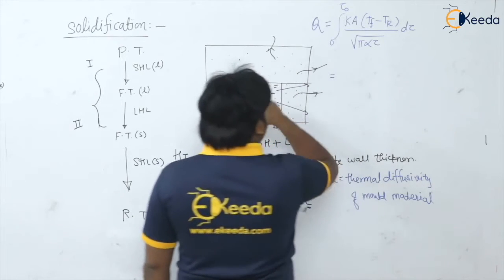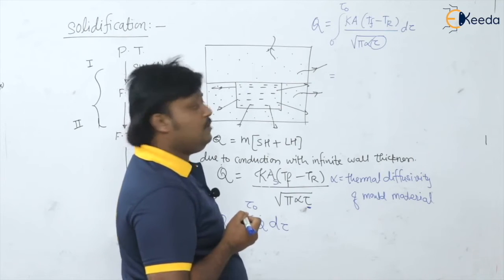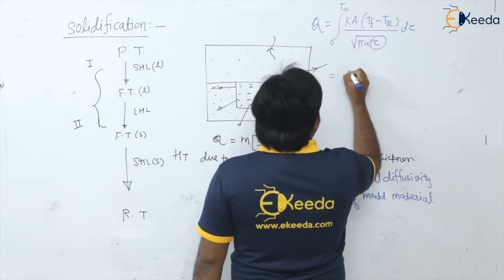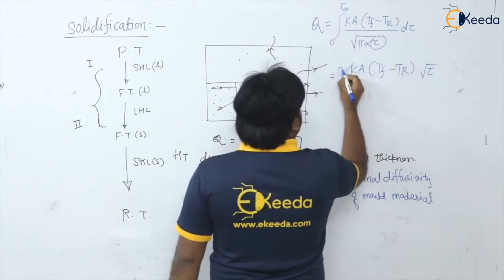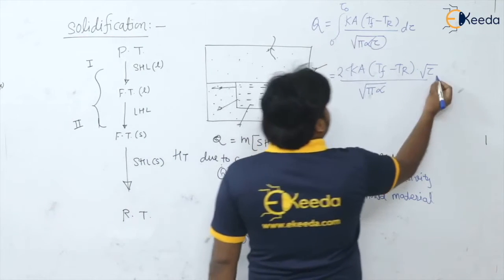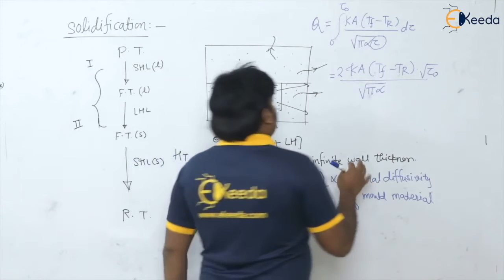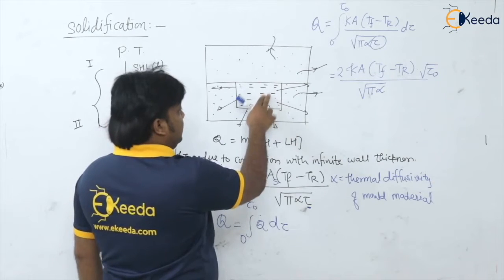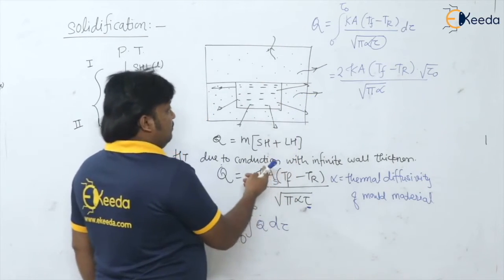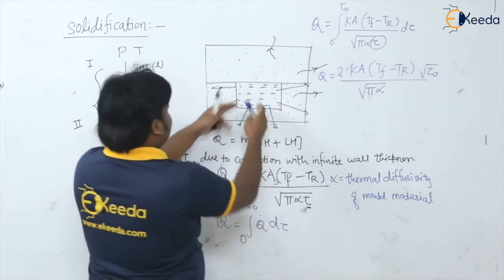Integrating this expression, the variable is 1/√τ and we know the integral of 1/√x is 2√x. So we get: q = k · A · (Tf − Tr) · 2√τ₀ / √(π · α). After applying the limits (upper limit τ₀, lower limit 0), this gives us the total heat conducted away by the molding sand to the surroundings through conduction with infinite wall thickness.